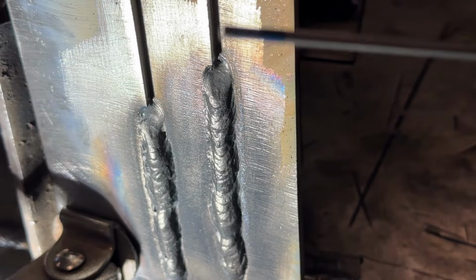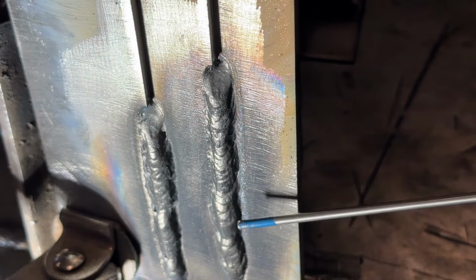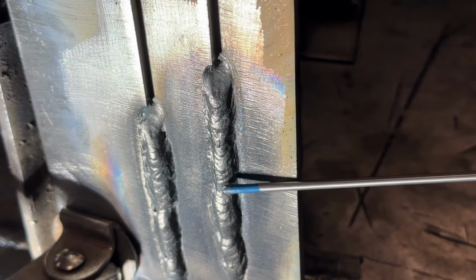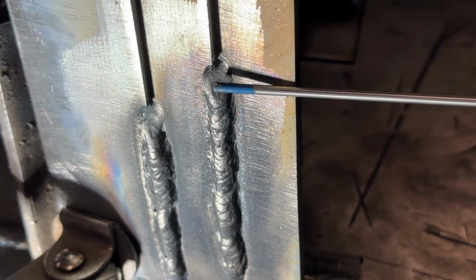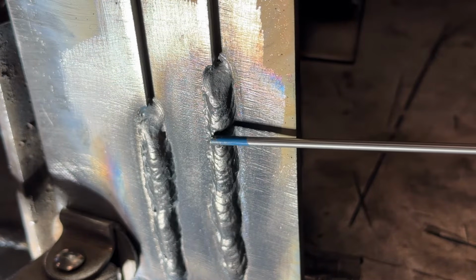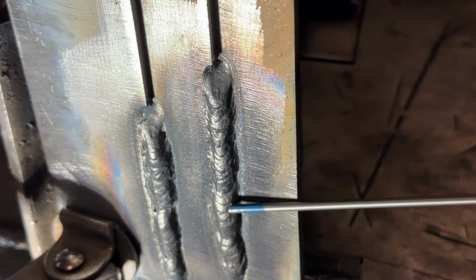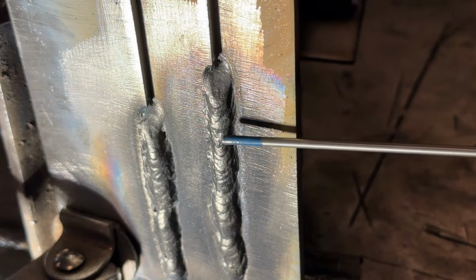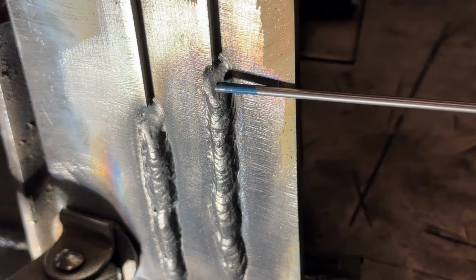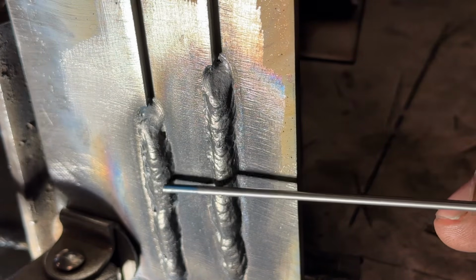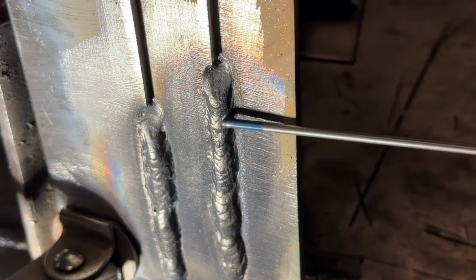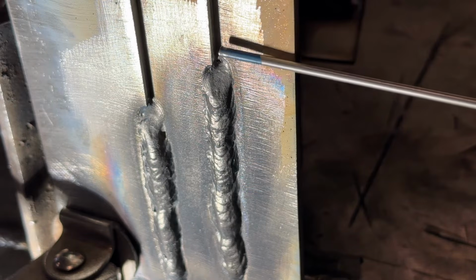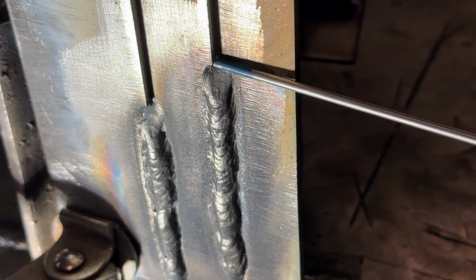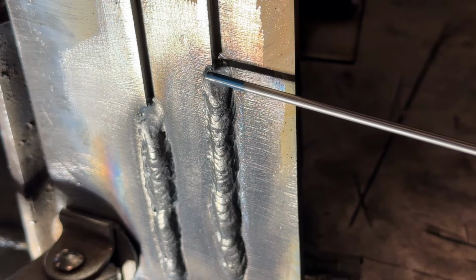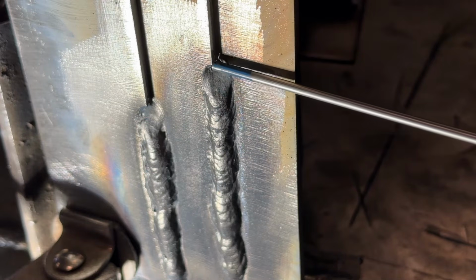So let's take a look at what we got. Now, this weld from about this point up is exactly what we want to be aiming for. Down here, my travel speed was a little bit inconsistent, but this is what we're looking for. If you look, it's not humped up at all like this weld is, so that's looking really good. If my wire was aimed at the center here, you can see our melt over the edge was very minimal.